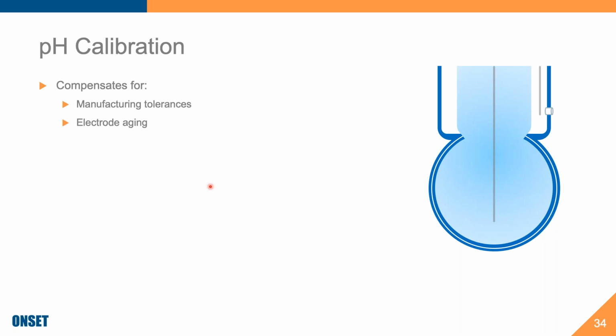In addition to which, you want to compensate for electrode aging. A brand new pH electrode is wonderful because it's shiny new. Hopefully it's conditioned and your outer gel layer is nice and hydrated, as is your inner gel layer. You don't have any cracks. But as you use a pH electrode, that glass, which is hydrogen sensitive, will start to break down, because it is a silica glass, and it will age. And as that happens, you want to compensate for that aging by calibrating.